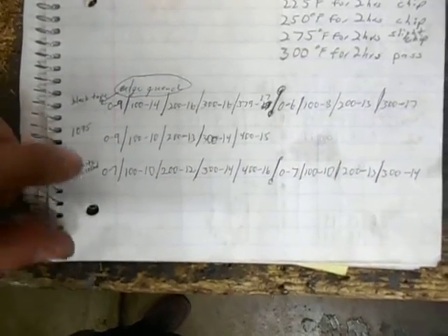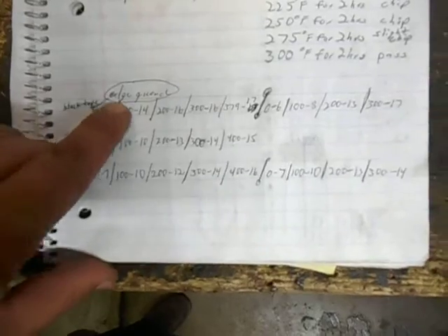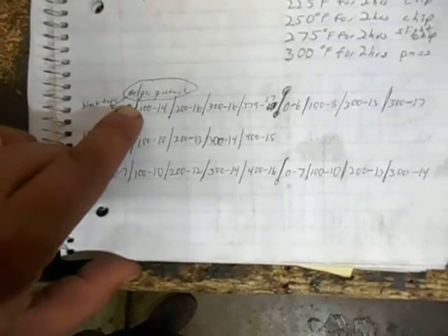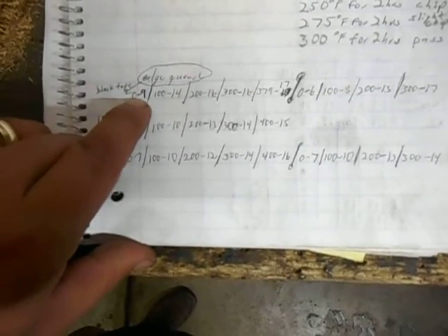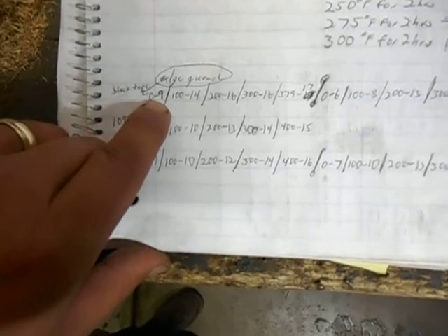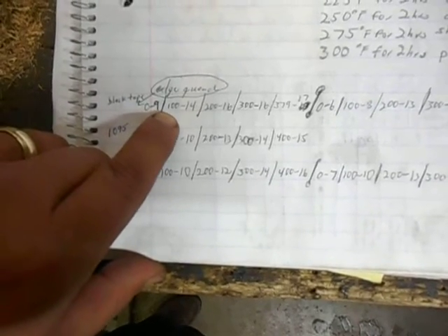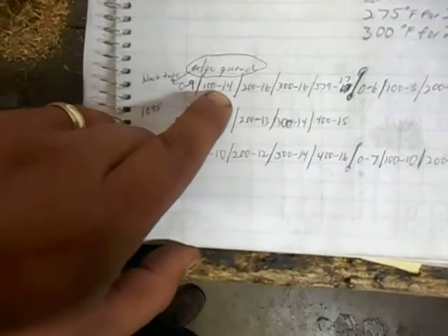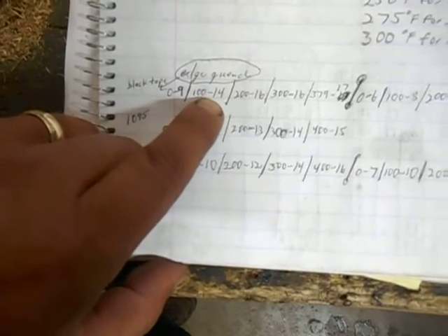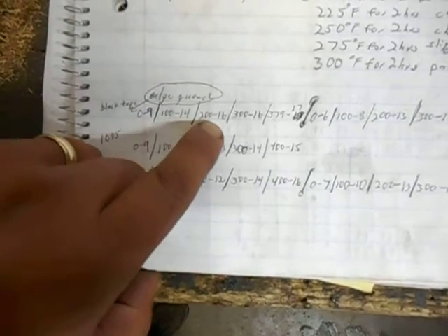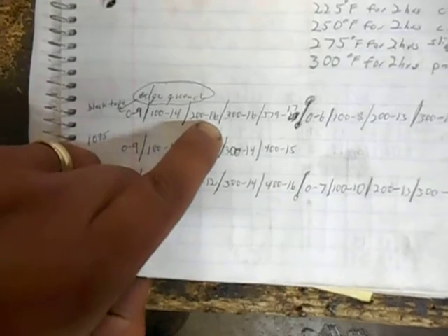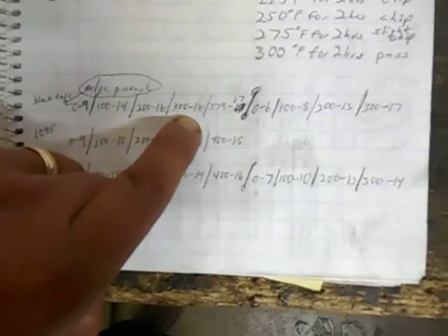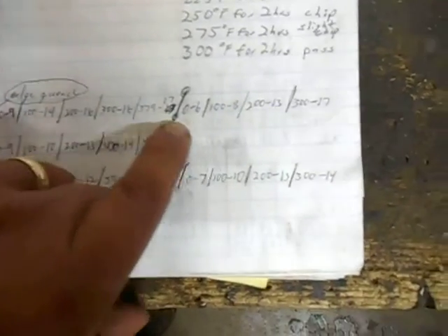And you can see the cut testing here. I'll just, because you guys can pause it and rewind it and look at this again. But basically, the one with the black tape was an edge quench. The first cut took 9 pounds of force to make the cut. The 100th cut took 14 pounds of force to make that cut. The 200th cut took 16 pounds, and so on until I quit.